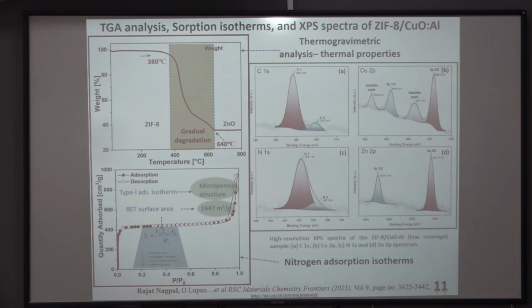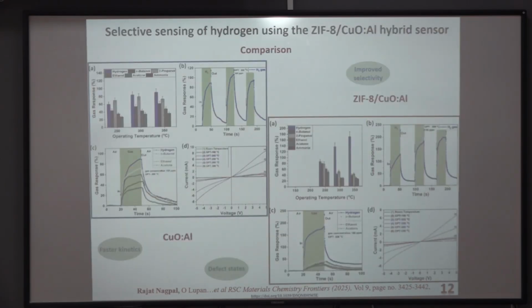Now to get more insights about the chemical information, here we can see XPS spectra. The high resolution XPS spectra gives information about the bonding environment for different entities in the hybrids, and copper 2p coming from copper oxide aluminium, it confirms the 2+ oxidation state, and zinc 2p coming from ZIF-8, its 2+ oxidation state is confirmed through this high resolution spectra.